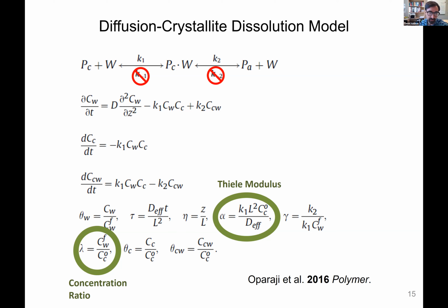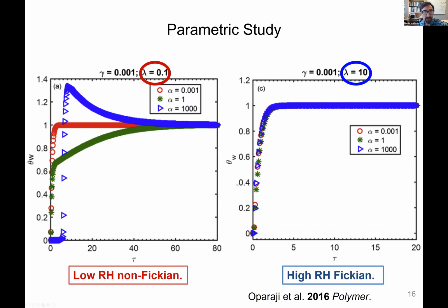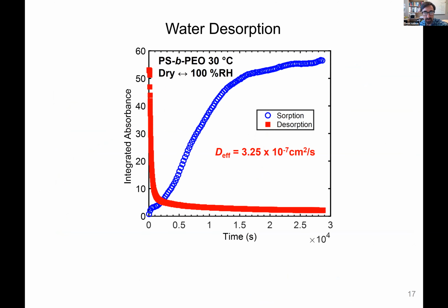So we saw this effect of final humidity. And if we do a parametric study, what we see is that when we're at lower humidities, or lambda is small, if diffusion and reaction are of similar magnitude such that the Thiele modulus is about on the order of 1, then we see this apparent non-Fickian diffusion, very reminiscent of what we saw in the experiments. Whereas even when we're at this alpha of 1, when lambda is large, when we go to high humidities, everything appears to be Fickian. So we think this really captures what we saw in experiments.